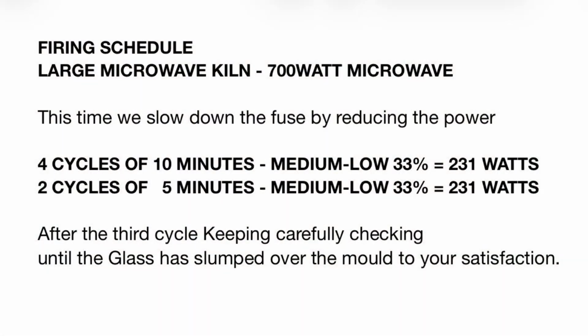So as I mentioned earlier, we need to slow down our fuse for the slump, and to do this we reduce our power down to medium low, which in my microwave is the equivalent of 231 watts, and we'll do 4 cycles of 10 minutes and we should just start to see the glass begin to slump over the mould, and then a further 2 cycles of 5 minutes should do it. But keep checking from about the 3rd cycle to ensure that your glass is slumped satisfactorily.